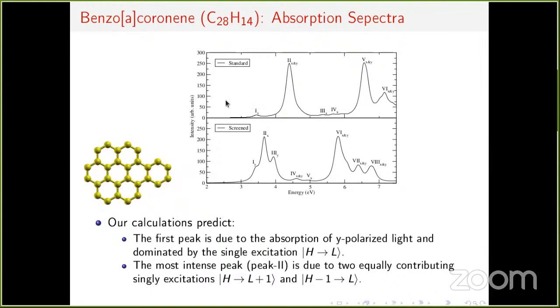Here is the entire calculated optical absorption spectrum of benzo-A-coronene. On top we have results using standard parameters, on the bottom with the screened parameters. Our results agreed more on the optical gap with the screened parameters, so we expect those results to be true. The first peak in all the calculations is Y polarized, Y direction being this vertical direction, and is dominated by the single excitation, the HOMO to LUMO transition. For the screened parameter case, the most intense peak will be this one.